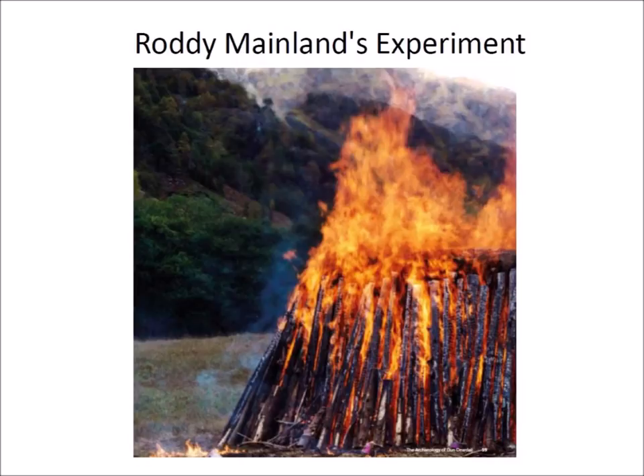A safety watch was maintained through the night, during which time 90% of the wood was burnt away, leaving a smoking core. At midday the next day, light rain had quenched the fire completely, but there was still heat within the core. Inspection of this material failed to provide any evidence of vitrification. 6 days later, a trench was dug through the still smoking core, which was still too hot to touch, but again there was no vitrified material.